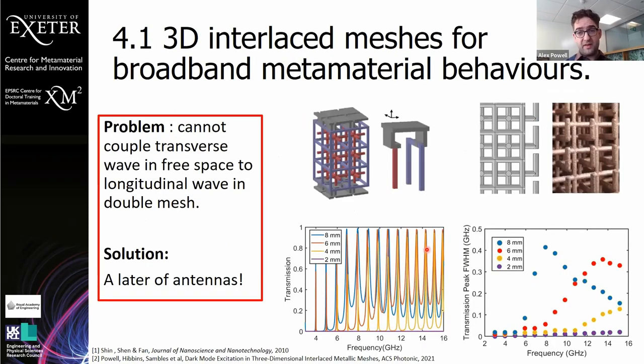Then we wanted to do that with the double mesh. But as I mentioned, the problem with this is that it's a longitudinal mode, so it's difficult to couple to that. You need some kind of matching layer to move from a free space transverse mode to this longitudinal mode in the structure. And so the solution we came up with was to have a layer of antennas on our structure.